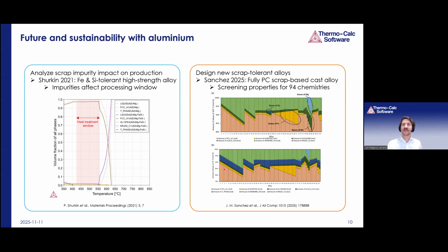Here at 500 degrees and 25 degrees. So at high temperature, you can look at the detrimental phases that will form during the cast, and also homogenization windows. And at low temperatures, you might look at other phases that can be problematic forming at lower temperatures. And they also looked at other important properties such as the density of the alloy. So they made a castable, good strength, fully scrap-based alloy using these tools.